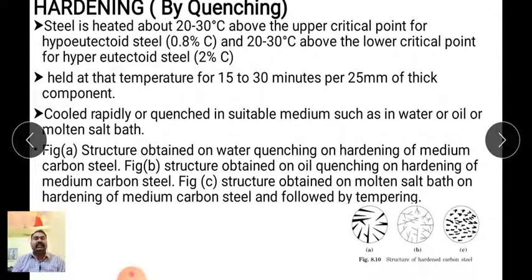The next heat treatment process is hardening, and it is also known as hardening by quenching. In the case of the hardening process, the heating process we will follow is explained over here. The steel is heated 20 to 30 degrees Celsius above the upper critical point for hypoeutectoid steel, and 20 to 30 degrees Celsius above the lower critical point for hypereutectoid steel.